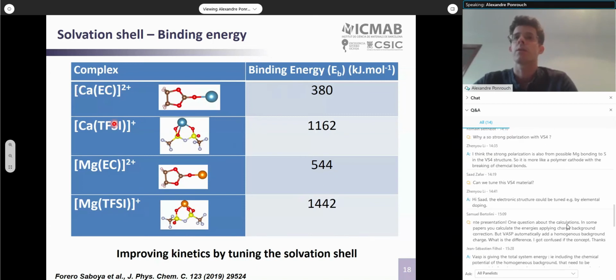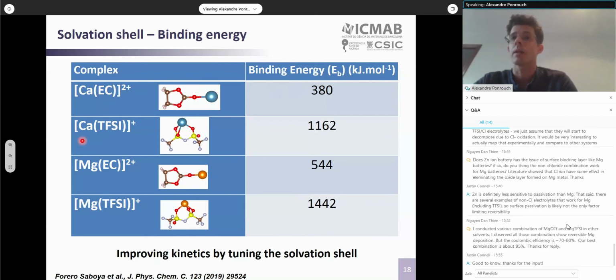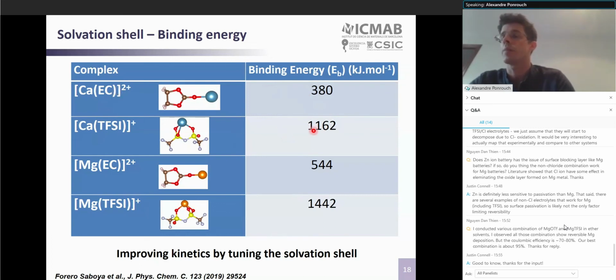And here you can see that for the contact ion pair case, the calcium TFSI complex, we have a binding energy about 3 times higher than for the complex containing a solvent molecule. So we do expect a significant negative impact of the formation of contact ion pairs on the calcium plating and stripping when contact ion pairs are present.